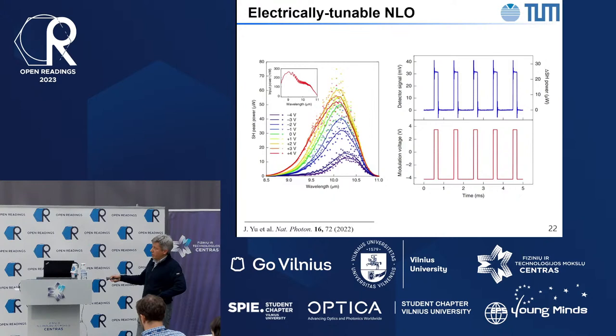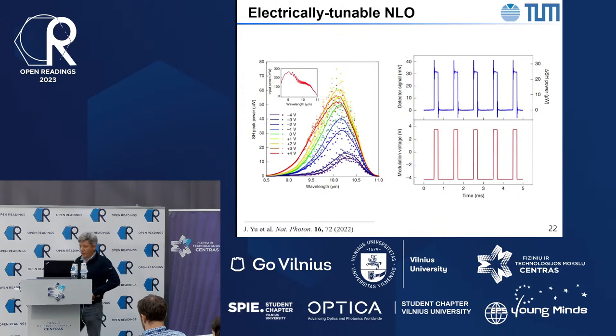This is experimental results. Laser was tuned and second harmonic intensity was measured. And you can see that at different voltage, second harmonic response has different values. You could move to 9.5 microns, and then you can modulate the second harmonic response from zero to maximum. Well, this is the second harmonic detector signal, and this is the modulation voltage. So you can vary the nonlinearity of your crystal.